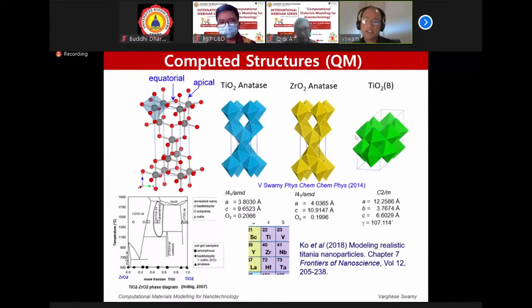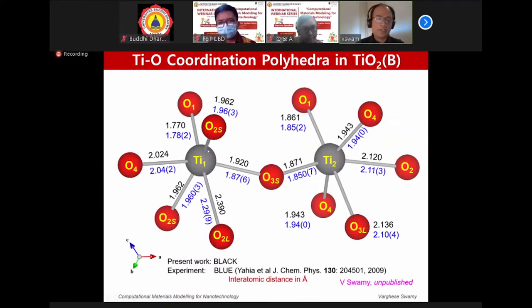I also mentioned titanium dioxide bronze, or B structure, earlier, which behaves very similarly to anatase. So this is what I did. I computed these structures. And in fact, this is the polyhedron, the coordination of titanium in the TiO2 B structure. There are two types of polyhedra here, characterized by Ti1-O and Ti2-O structure.